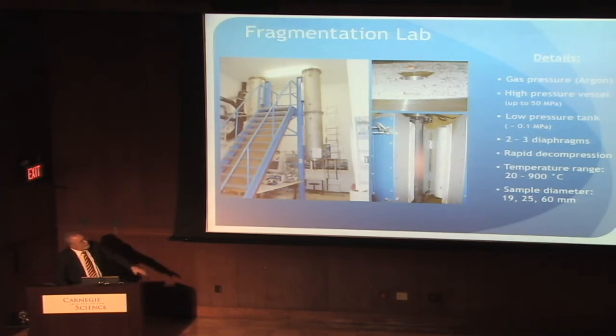We have membranes that are sitting between the high-pressure bomb and the atmospheric tank, and we let them fail due to a slight pulse in pressure that we give to an intermediate diaphragm. The bottom line is the sample sees nothing, the membrane breaks, and then explosively and at high speed, a decompression front rips into the sample and actually tears it apart due to the pressure gradient.